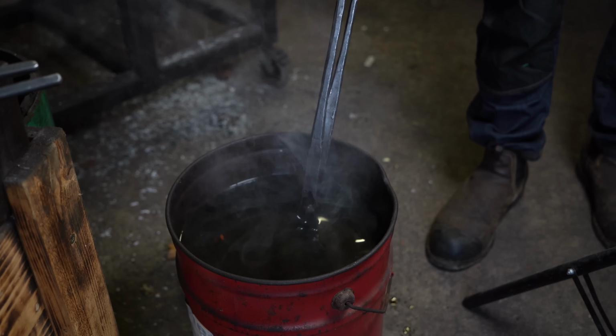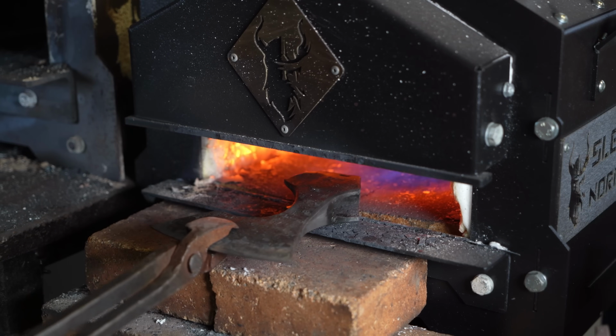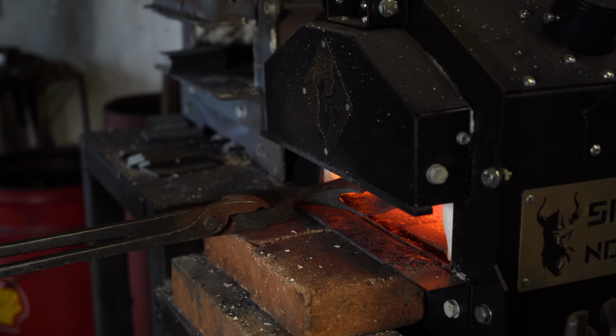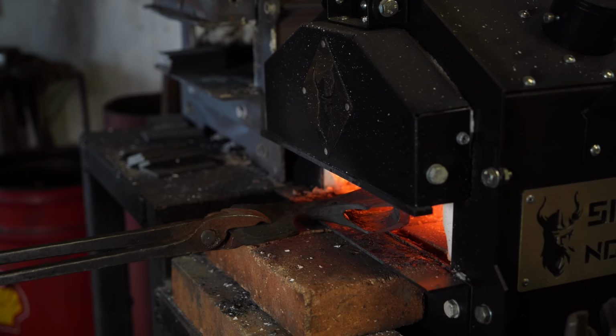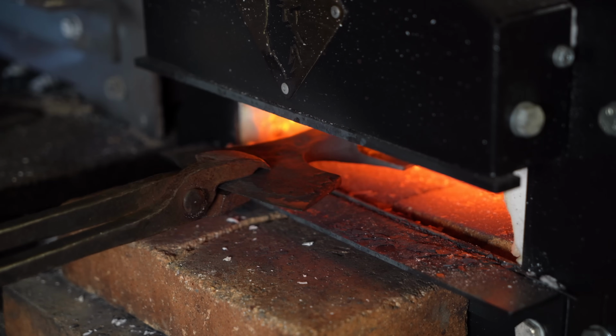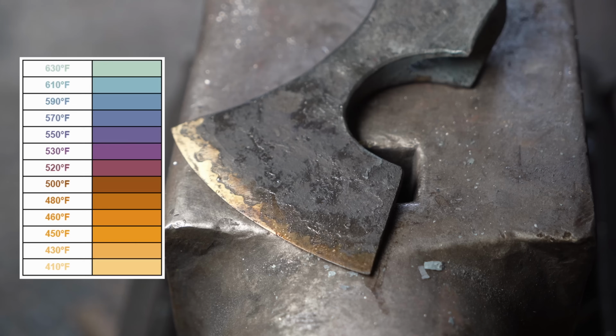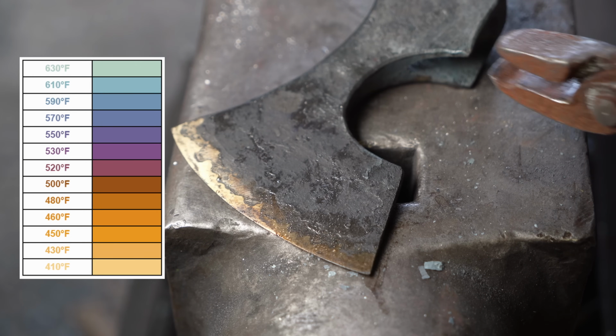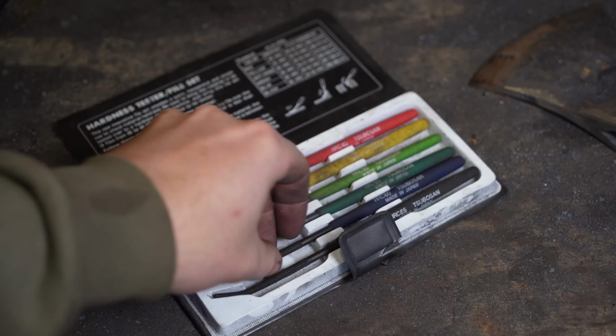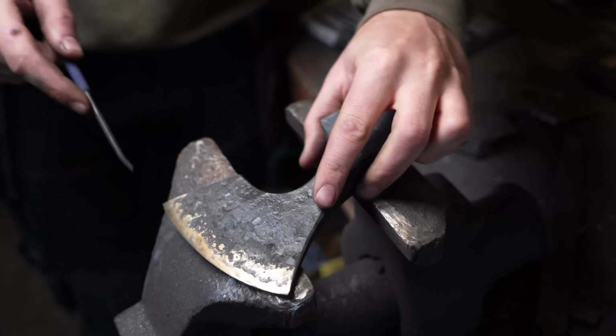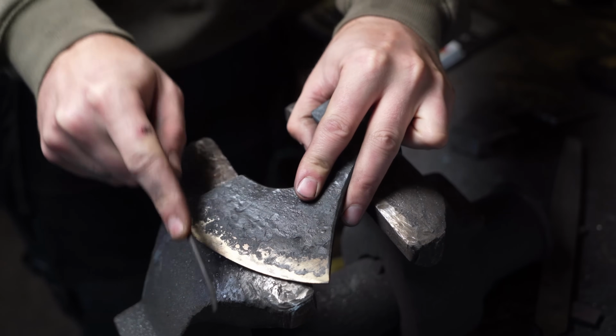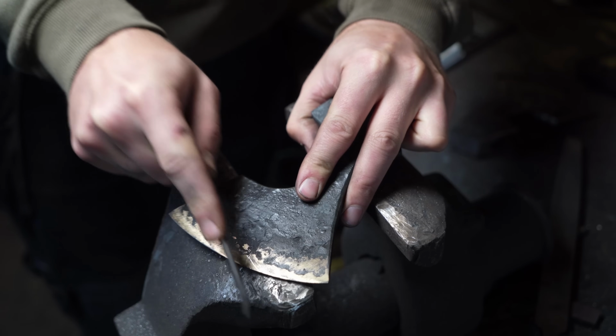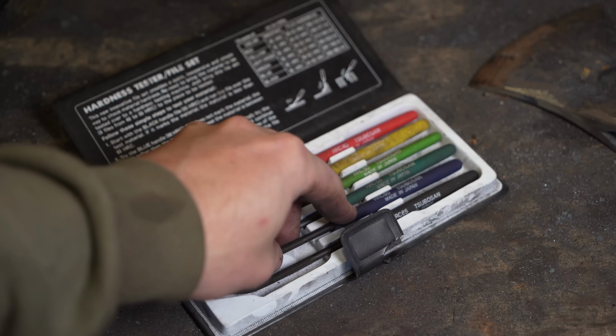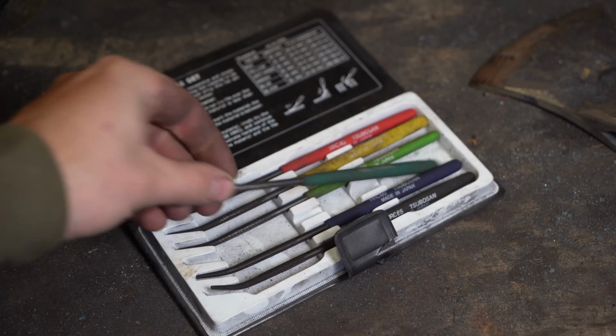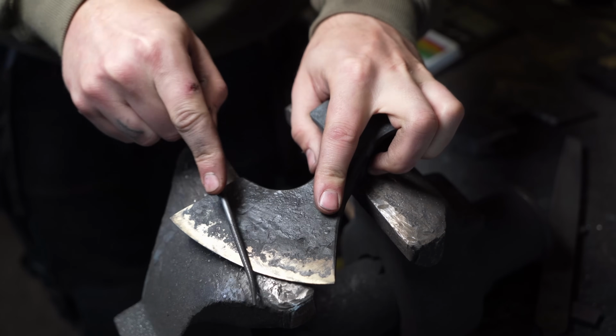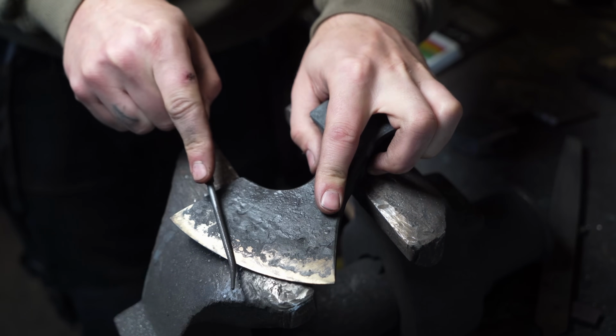To temper the blade, I first use some sandpaper on the edge so I can see the clean steel. I then stick it back in the forge, carefully watching the temper colors on the blade. To test the hardness of the blade, I use my Japanese Rockwell files. It gives you a rough idea how hard the edge is. If the file bites, it's softer than the file. If it skates, it's harder. In this case, it seems to be around 55 Rockwell.